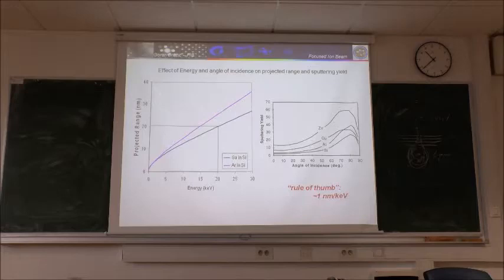Why is this important? Imagine that you want to prepare a TEM, meaning transmission electron microscope, lamella assembly. If you use high energy ions, you will end with material that suffers somehow, could be destroyed, could be amorphized. In the range of 20 nanometers, it's much too much. For transmission electron microscope, maybe we can survive with 1, 2, 3 nanometers maximum. So we should be in that range here. Definitely below 5 keV, maybe 2, 3, or 1.